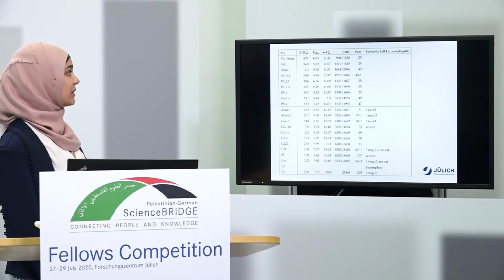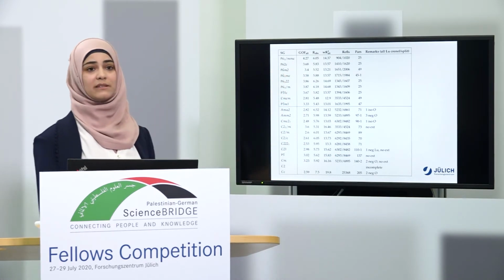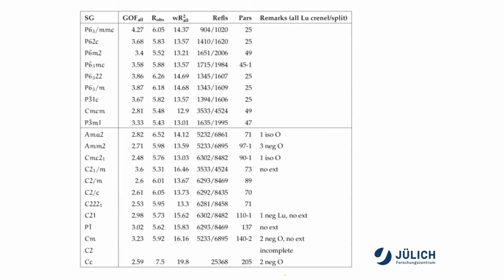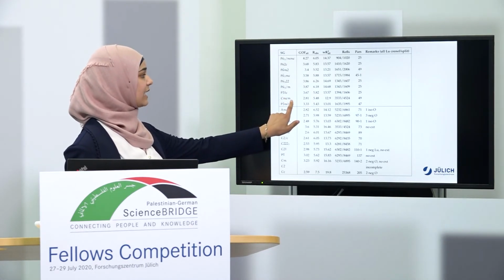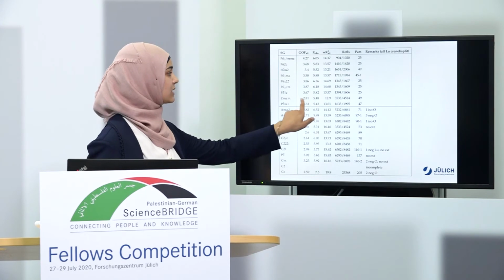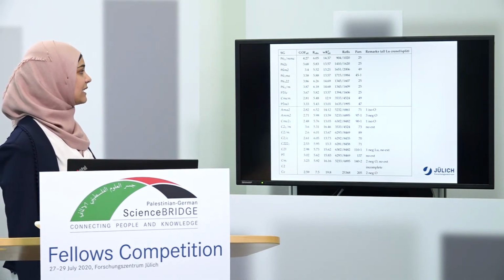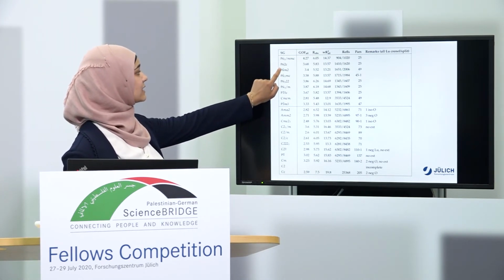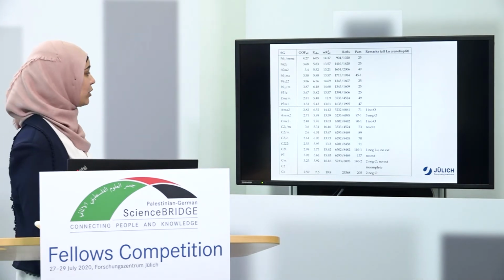This is what I did, and what you see here is the table summarizing all the lower symmetry space groups I tried, of course neglecting the superstructure reflections for the commensurate charge order type. The upper part shows that the orthorhombic Cmcm has the lowest residuals or goodness-of-fit factors, which basically means that every single space group that contains threefold rotation is broken. Threefold rotation is not there anymore.